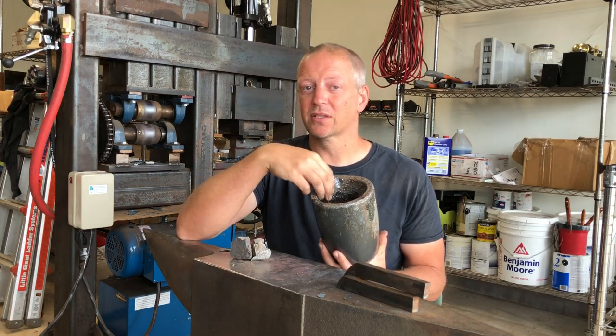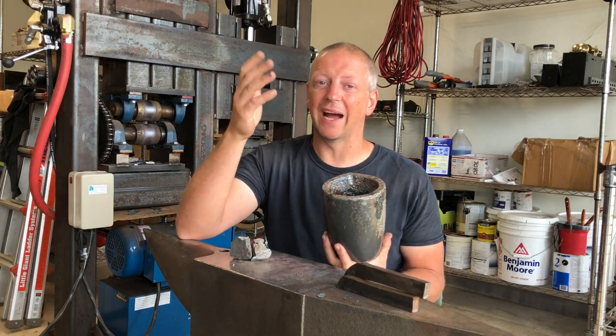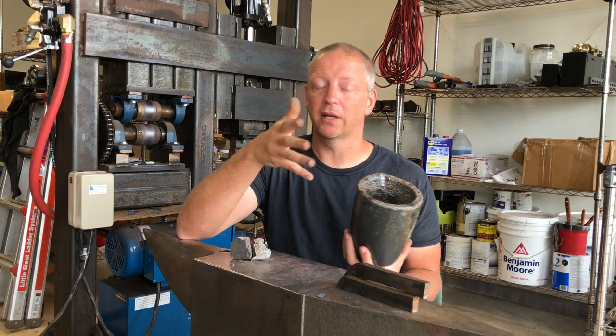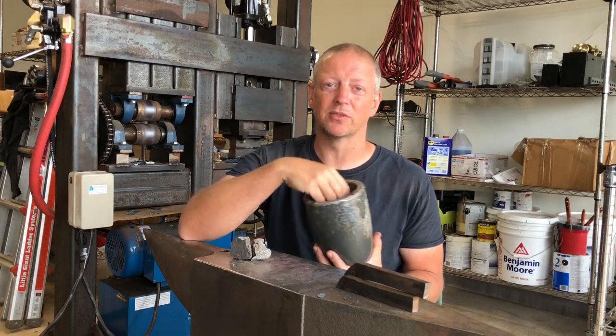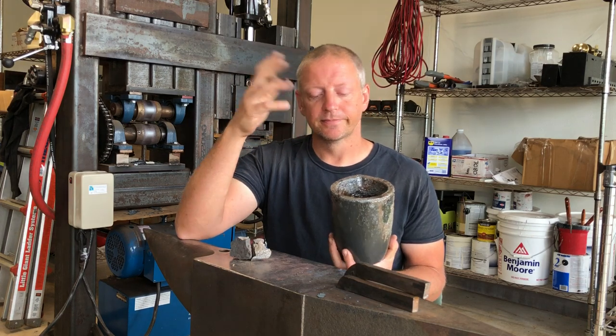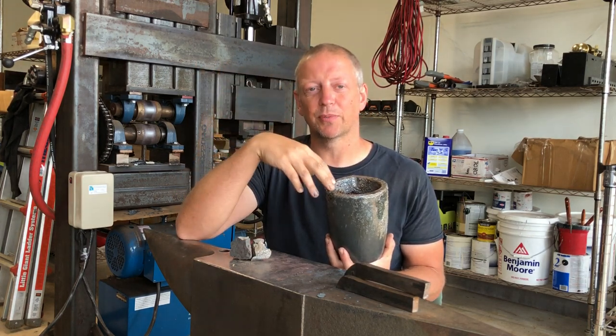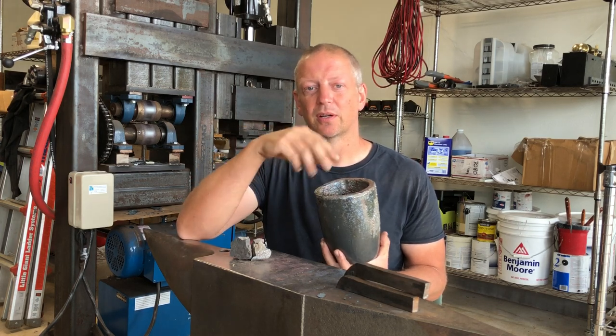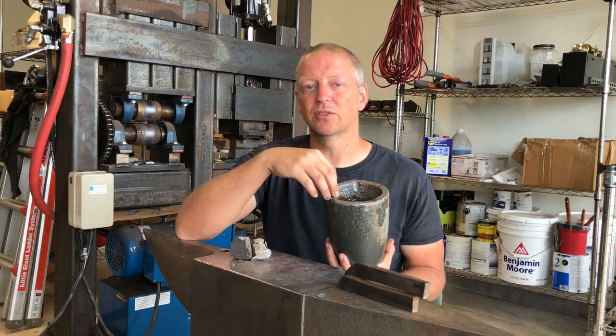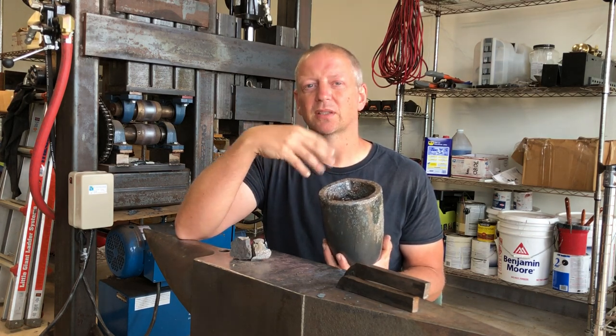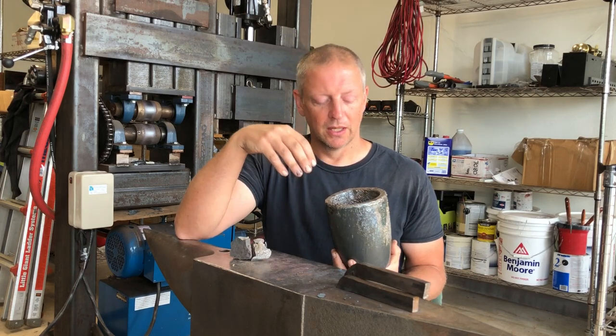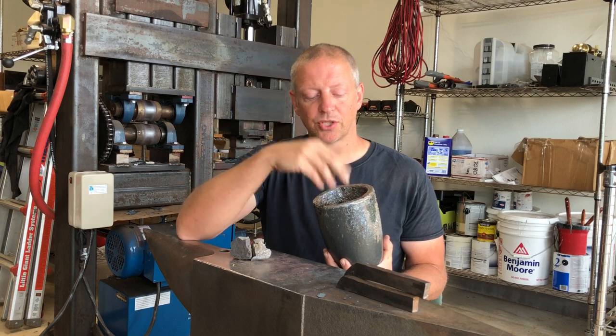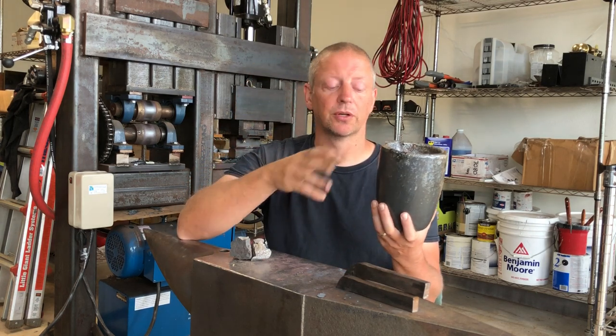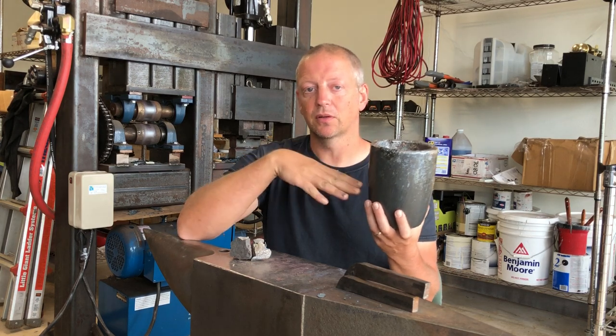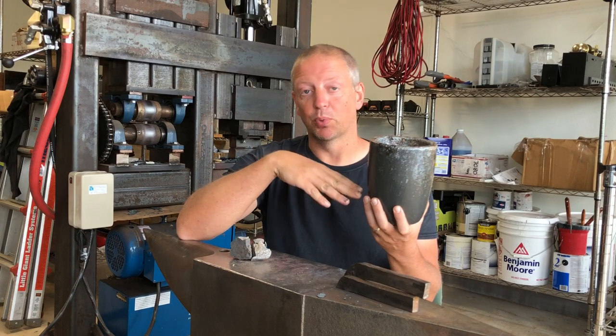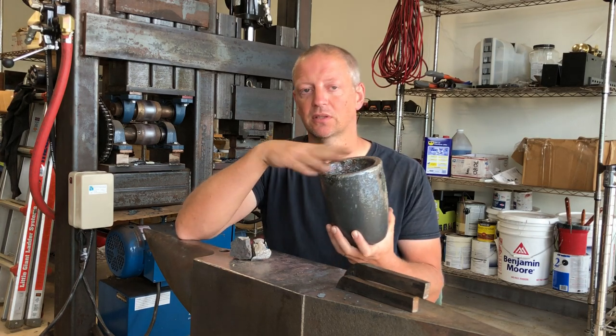That can be a slow process. It really depends a lot on the temperature of your furnace. If you're getting hot enough to just melt mild steel, it'll be fast. You'll melt your mild steel, it'll carburize with the charcoal, bam, you're done. If, however, you're not really quite hitting that temperature, it may take some time for the carbon to make its way into your wrought iron or mild steel, carburize it enough for it to melt. So basically, using charcoal, you're going to want maybe a few pieces of your mild steel, your charcoal, and then the main portion of your wrought iron or mild steel on top.